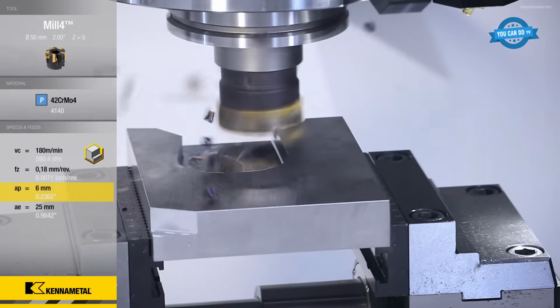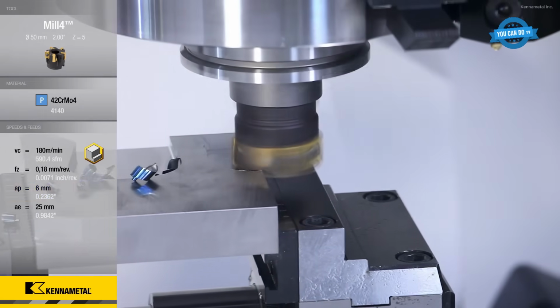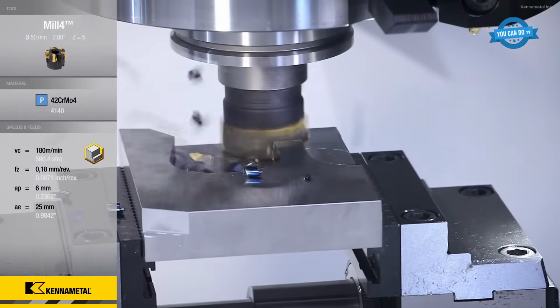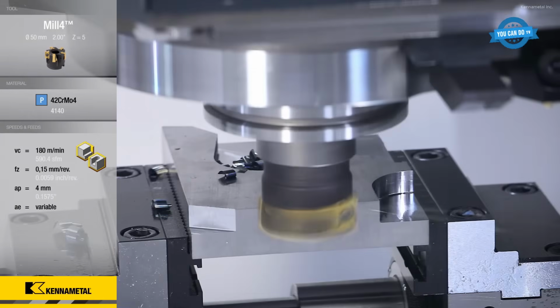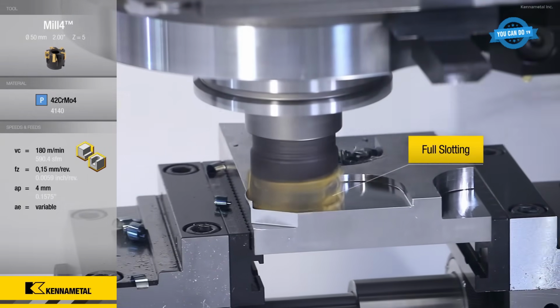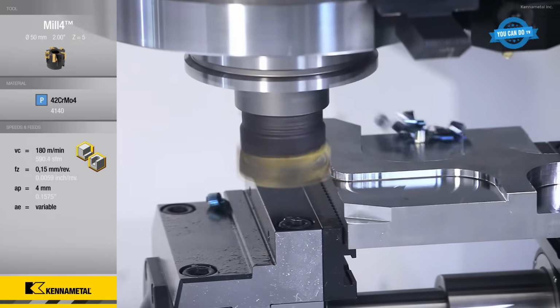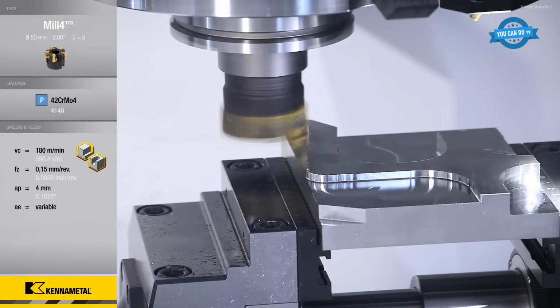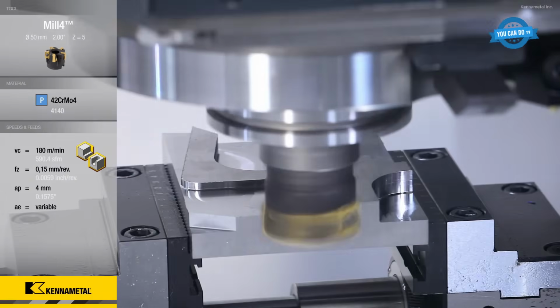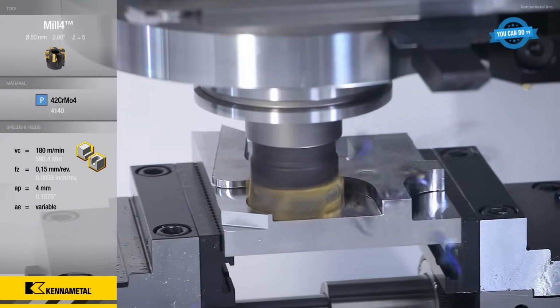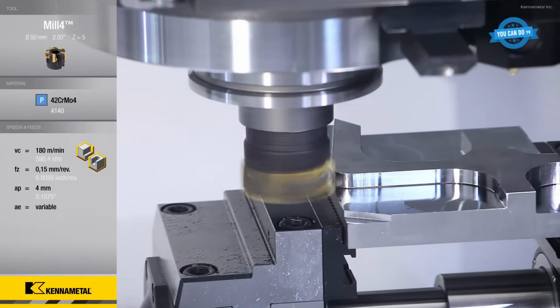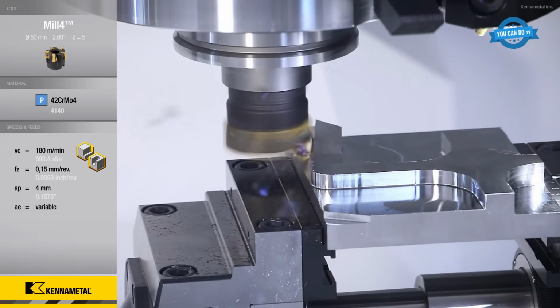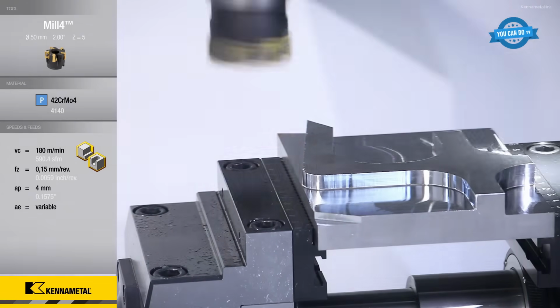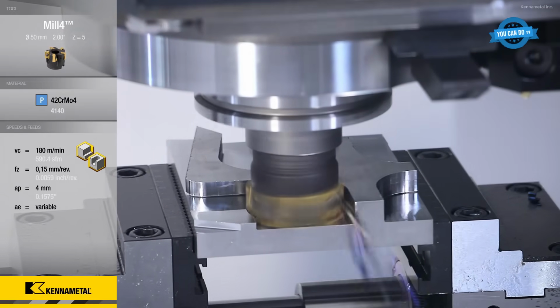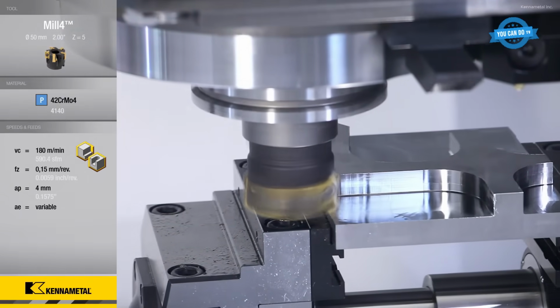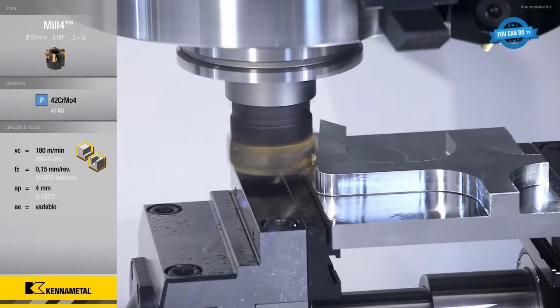The Mill 4-15 is highly versatile, with multiple corner nose radii and universal insert geometries, suitable for materials like 42CrMo4 steel. Tested speeds and feeds include cutting speeds up to 180 meters per minute, feed per tooth of 0.15 to 0.18 millimeters/rev, and axial depth of cut from 3 millimeters to 12 millimeters. This platform excels in full slotting and variable width applications, delivering a powerful solution for high-performance milling in demanding environments.